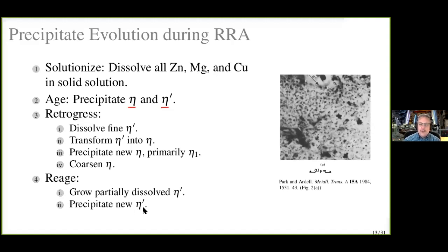So by the end of this process, compared to the T6 condition, which is basically my T6 condition right here, I will have some coarse eta at grain boundaries. And then through the rest of the matrix, I'm going to have a mixture of somewhat coarsened eta that's pretty fine, and these new eta prime precipitates formed upon reaging. And that really gives good strength. And the change of the precipitate nature, particularly at grain boundaries, is what Park and Ardell attributed the increase in stress corrosion cracking resistance to.